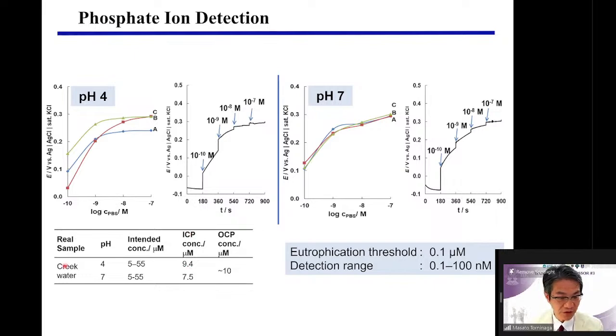So, the creek water at pH 4 and 7. In the ICP result, we observed this concentration. This is our sensor's result. This result is similar to the ICP result. So it means my sensor can detect the phosphate ion.